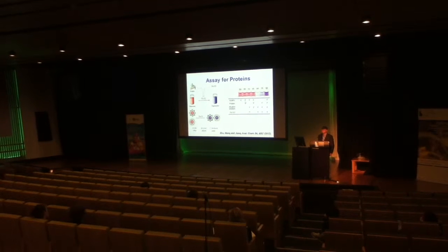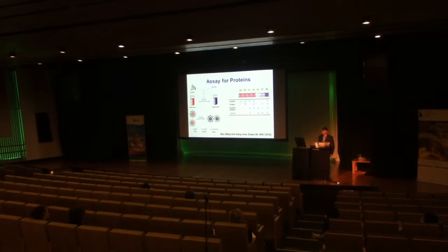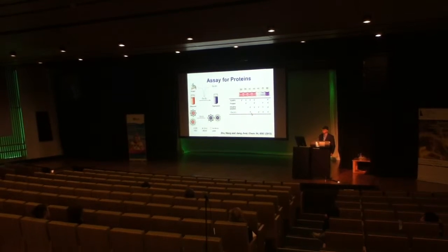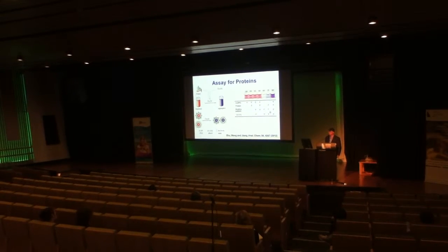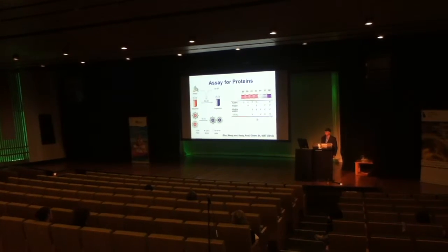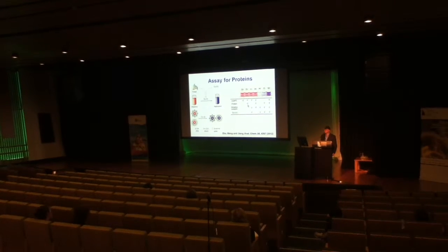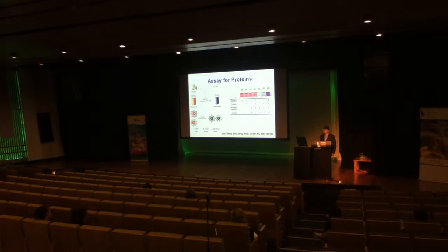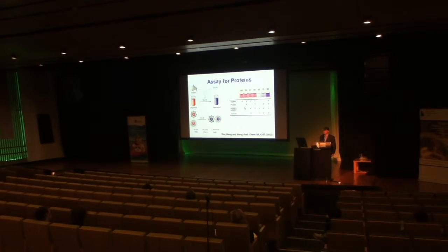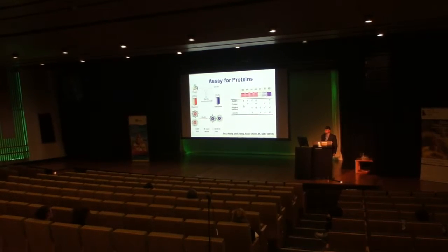So as you see in here, if we add in the gold nanoparticles, the proteins and a reductant plus the copper-2, only the ones where we have the presence of copper-1 have a change in color. The other solutions don't have changing colors. So this assay actually allows us fairly high sensitivity and a broad detection range.